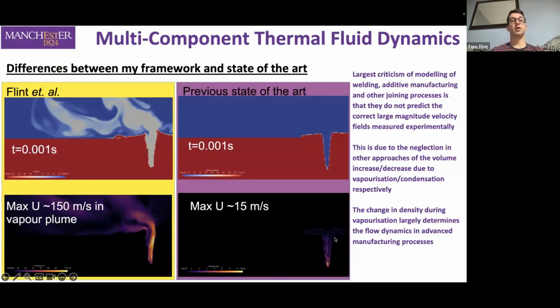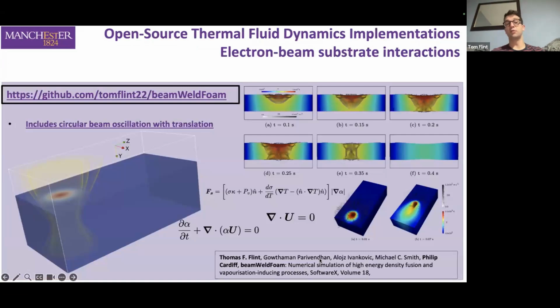So again, the simpler approach is just two phase, and our approach is fully multi-phase. We're resolving the vapor phase, whereas the simpler approach doesn't resolve the vapor phase. And then they have to apply what's called a phenomenological recoil pressure term, because they don't actually capture the physics of the recoil properly. As you can see, our approach captures this really high velocity field, and that's the main criticism of the other approaches out there, that the velocity field in the keyhole region is not captured properly. But we release these open source.